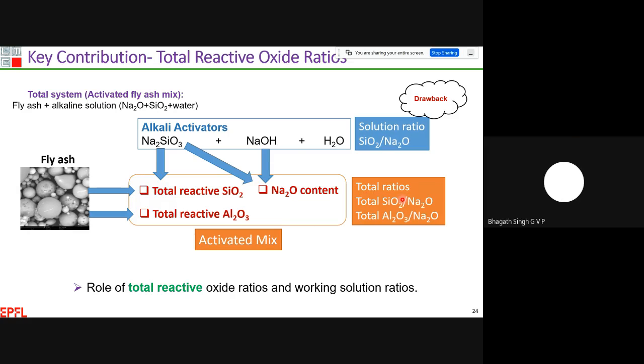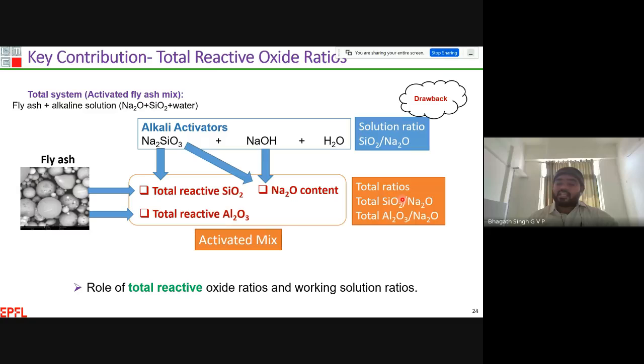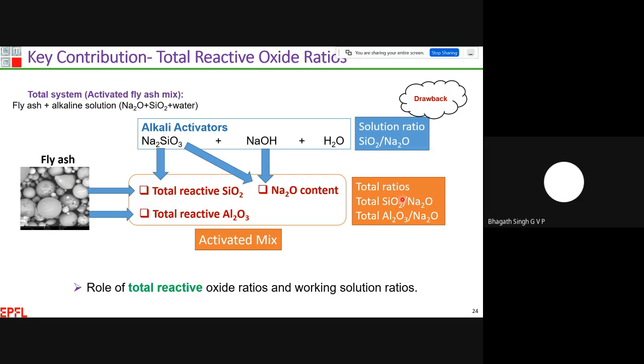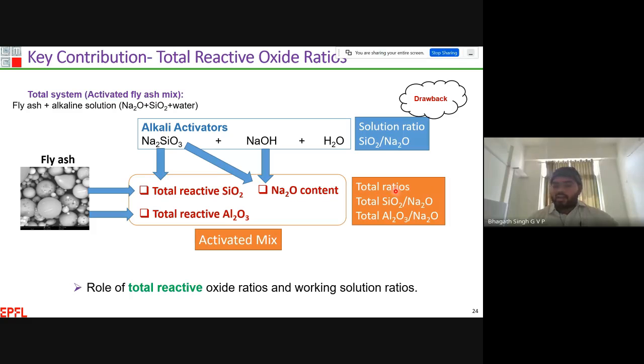These are all globalized ratios. They can be useful for any source of fly ash, and they will give proper results irrespective of the fly ash source. To prove this point, I have carried out some experiments using different source fly ashes. I tried to apply what the literature says, like working solution ratios, and I used my own ratios irrespective of fly ash source, to prove which ratios are important in this research field. I will show all those results in the coming slides. Overall, the total reactive oxide ratios approach introduced to this research field gives globalized ratios that can be applicable to any source fly ash.